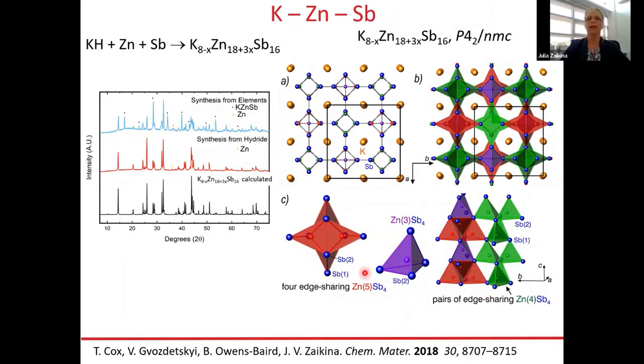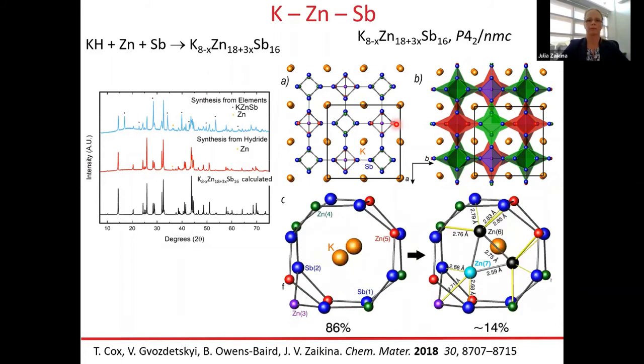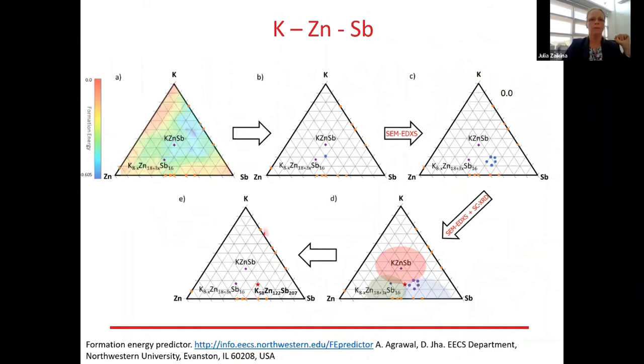This is a zinc antimony framework consisting of edge and corner sharing tetrahedra of zinc, with the potassium filling up the channels. And of course, this is not the real structure, but rather an idealized structure, because in 14% of the cases the potassium cation is replaced with a zinc triangle, which is located right in the center of that channel.